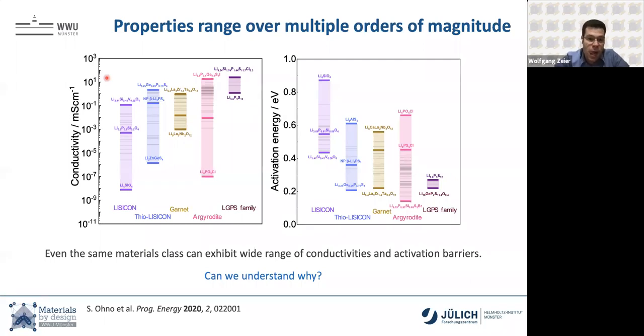battery operation. And if you plot literature data of conductivities for various materials classes, let's look at the argyrodites class that I'll show today. Within the same structure type, your conductivity branches over orders of magnitude. And your activation barrier does as well, even though this is the same structure type. And so our job is to always figure out why that is the case and which knobs we need to tune to push these ionic conductivities.